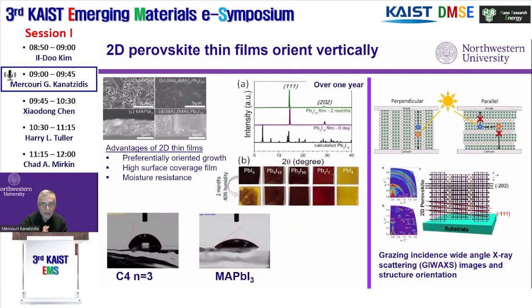Now, what can you do with the 2D perovskites? Because you might think, well, they're not going to be as good as the 3Ds. First of all, one thing that came out right away is that they're much more stable than the 3Ds. So that's interesting. They're soluble, so you can make thin films and cast them. And this is the first result we got in this diffraction pattern, where we noticed 2 things. First of all, the film did not have all the diffractions, did not have all the Bragg peaks. This black diffraction pattern is the calculated pattern. These are all the peaks that should be there. The film, when made, only has few reflections.